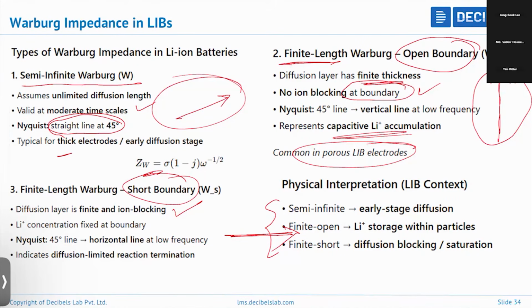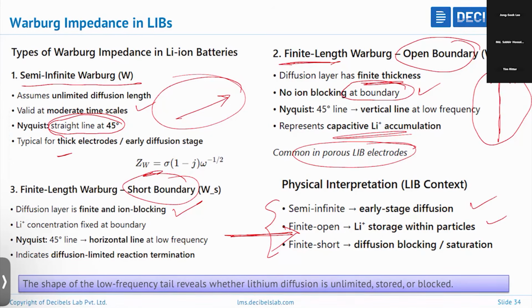Semi-infinite, briefly you can understand that it is early stage diffusion. Finite open means lithium-ion storage within the particles. Finite short means diffusion is blocked and it saturates. The shape of the low frequency tail, whether it is 45 degree or parallel to the y-axis or parallel to the x-axis, reveals whether the lithium-ion diffusion is unlimited, stored, or blocked. So this is the information that you can extract from the Warburg.